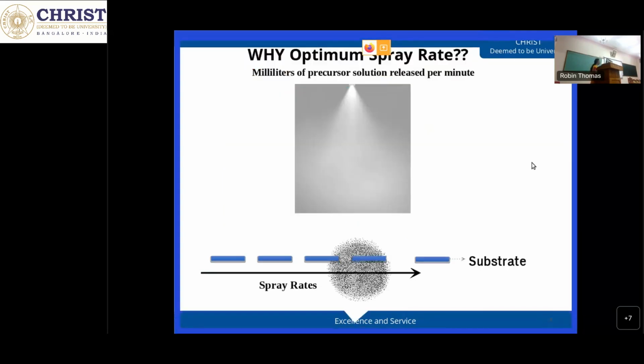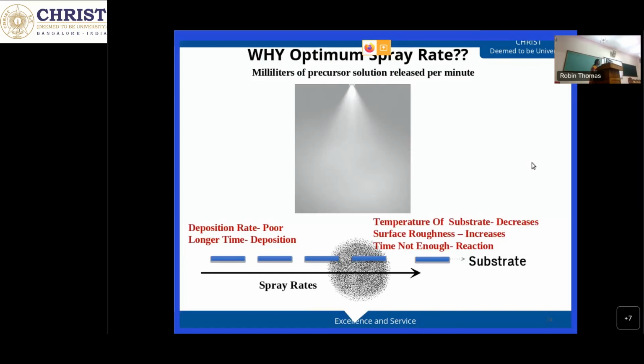Then comes the optimum spray rate. Spray rate is defined as the milliliters of precursor solution released per minute. If we need a film with a required thickness and the spray rate is very low, we have to deposit for a long time. When we deposit for a long time, the heating will change and can affect the film properties. And if the spray rate is very high, what will happen? So much solution falls onto the substrate that the substrate temperature will decrease, and that can cause other problems in films, like an increase in surface roughness. Moreover, the deposition won't be proper because there won't be enough time for complete thermal decomposition before the next layer of coating. So we have to optimize the spray rate also. Similarly, we have to optimize the molarity and the chemical composition before spraying onto the substrate.